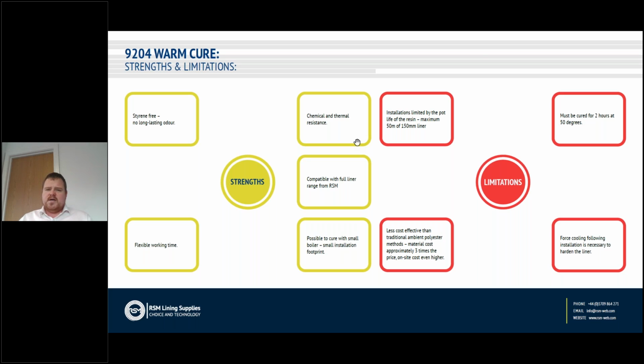In terms of limitations, obviously we can't line 500 meters of drain with the 9204. It has a limited working time, but we can probably get 50, 60 meters of 150. If we chill the resin down, we can probably do 60 meters of 225 diameter rehabilitation using this product. So it's a little bit less cost effective than polyester. And it also is necessary, with it being a heat cured epoxy, to cool the liner significantly prior to reinstatement. This is absolutely essential so that we don't have a situation where the liner folds in after installation.